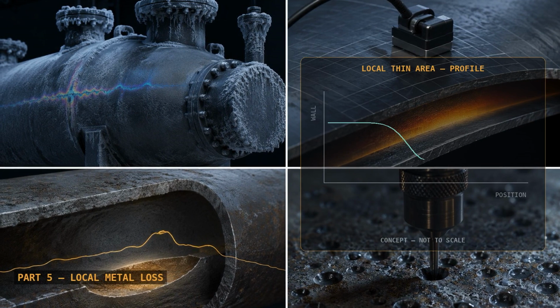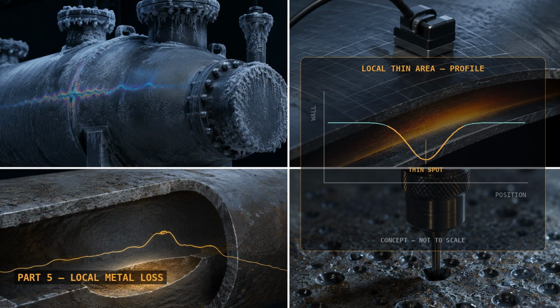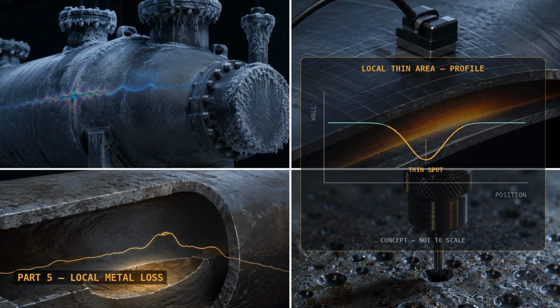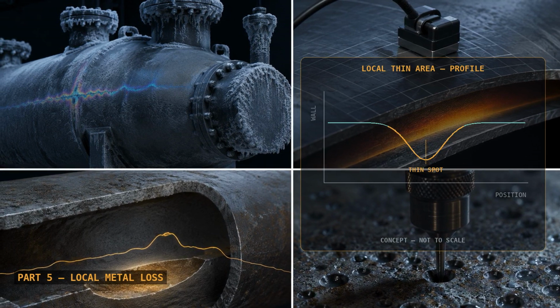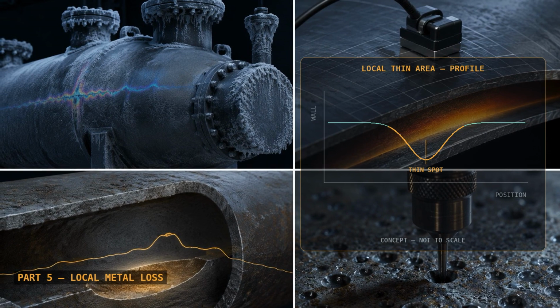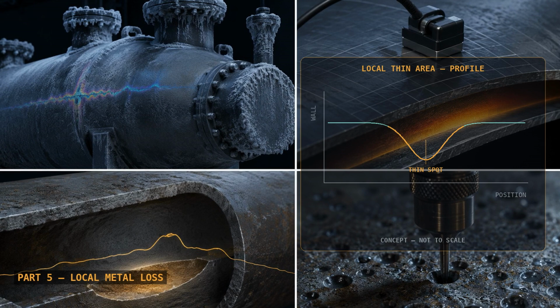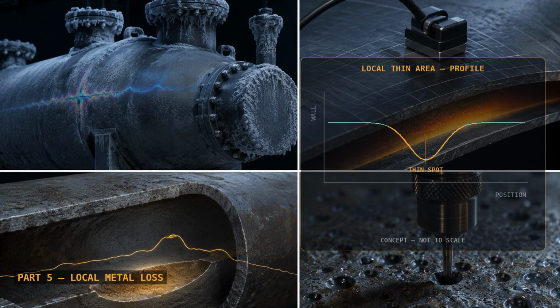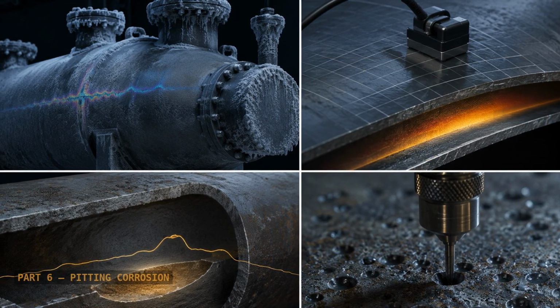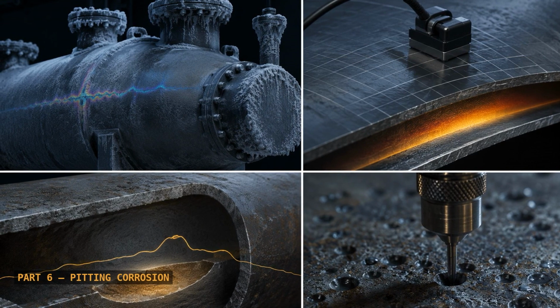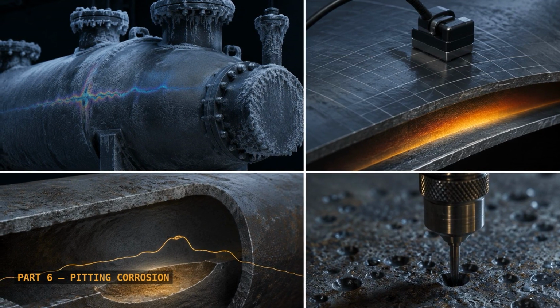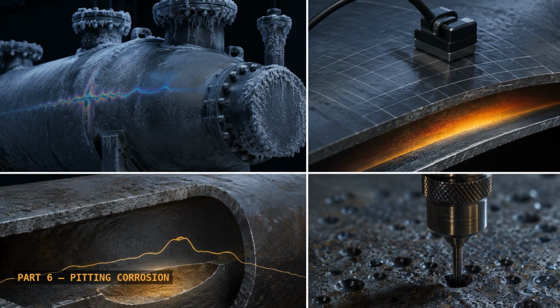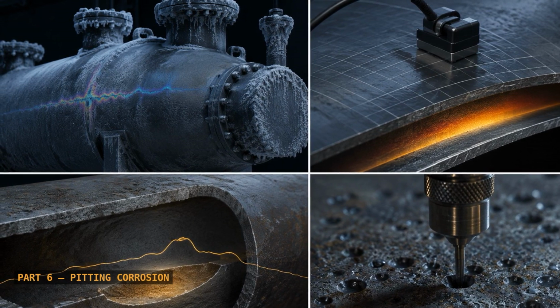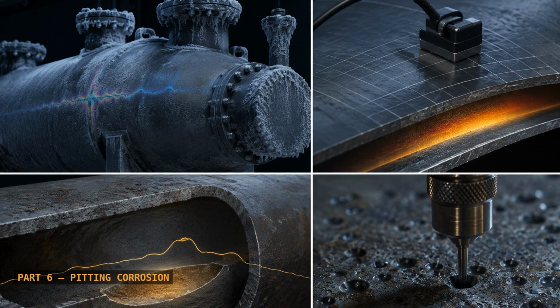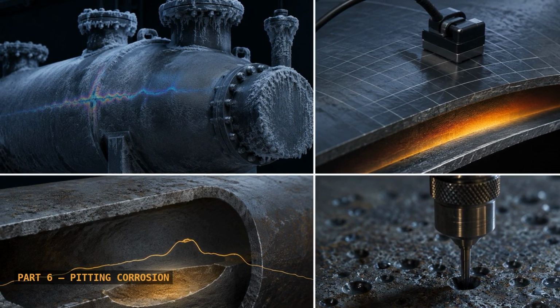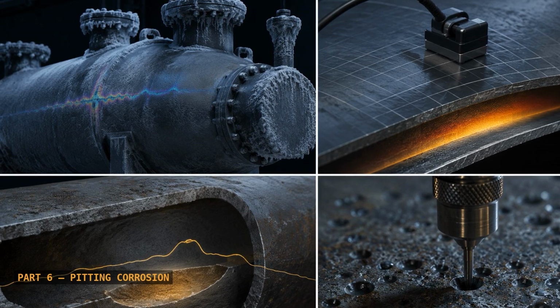Part 5. Local metal loss. A thin patch or groove surrounded by sound wall, mapped with thickness profiles. The question: is the thin spot small enough and the surrounding wall strong enough to keep carrying the load? Part 6. Pitting corrosion. Deep small area pits, chlorides, under deposit attack, tank floors, found visually with pit gauges and mapping. The question: are the ligaments between pits still adequate, and could a pit leak or start?